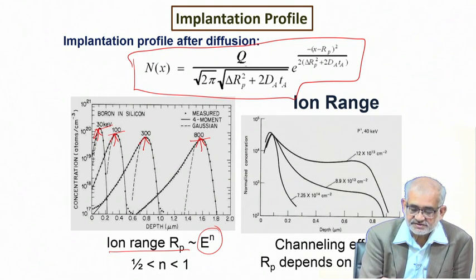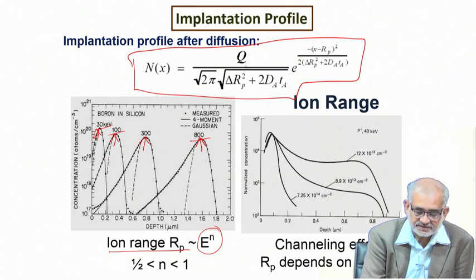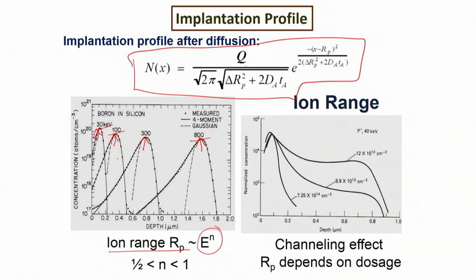What is also interesting is that usually all these peaks, particularly at lower acceleration voltage, are Gaussian and nearly coincide with the measured distribution. But when you go to very high voltage like 800 keV, the ideal Gaussian profile would be somewhat like this, but the experimentally measured profile will be lagging, will be different.